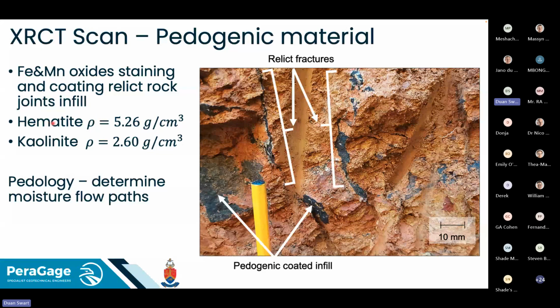Hematite is a very typical iron oxide that happens in ferrocretes, nodules and staining, with a density of 5.2, and kaolinite is 2.6. What we use this for is to determine where the flow happens, because it's very tough to do a triaxial and then see where the flow is happening. So using theories from pedology, we're trying to figure out where that boundary is: will the flow be homogeneous through the primary pores, or does it still follow the secondary structures from the relic rock structure?